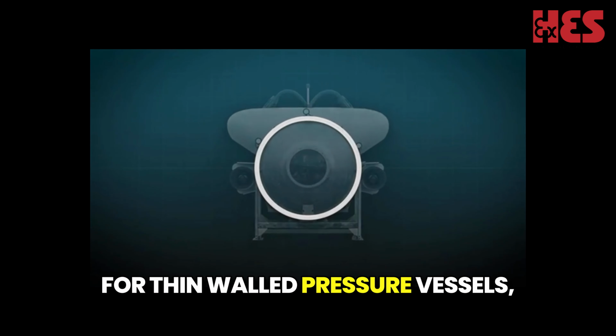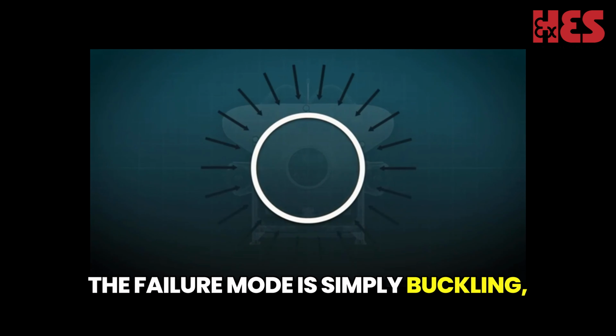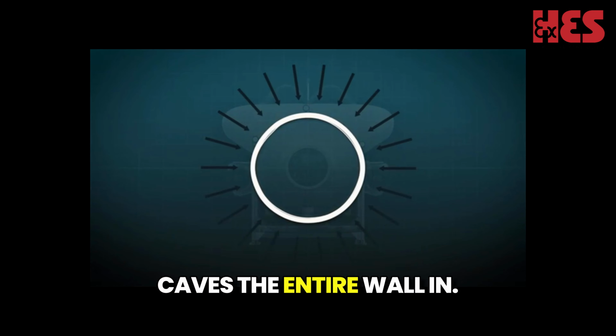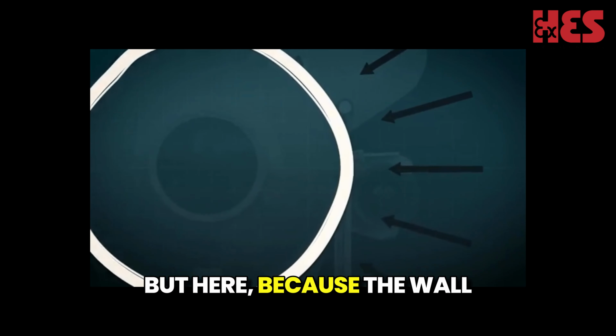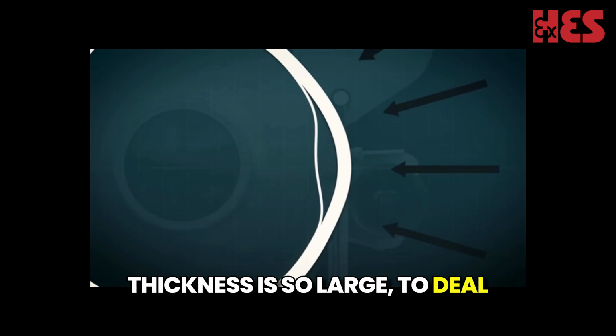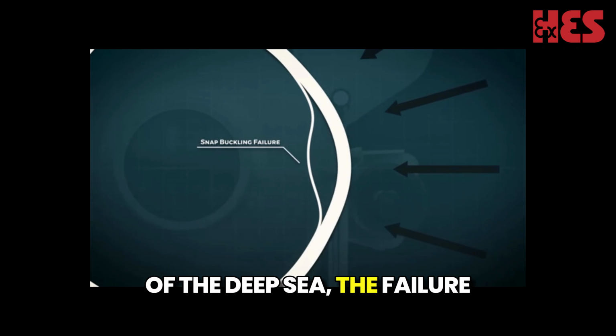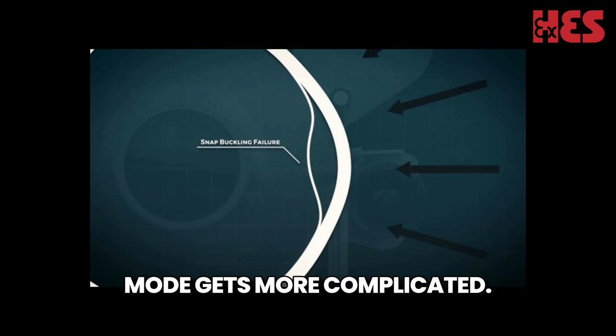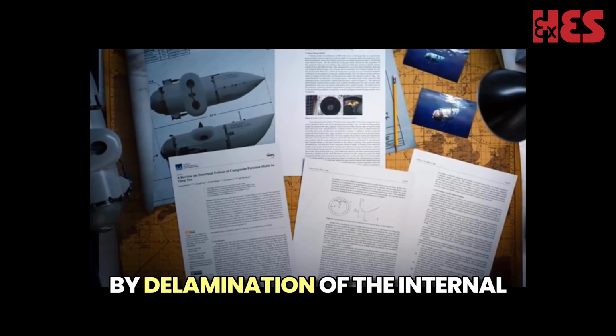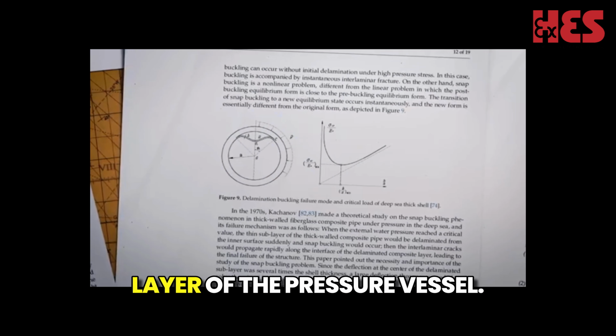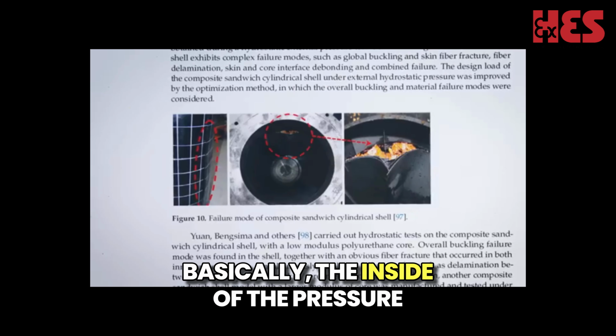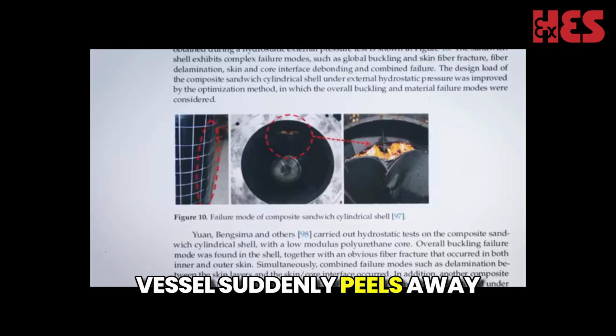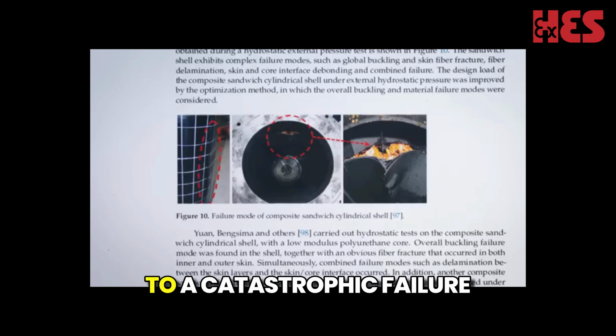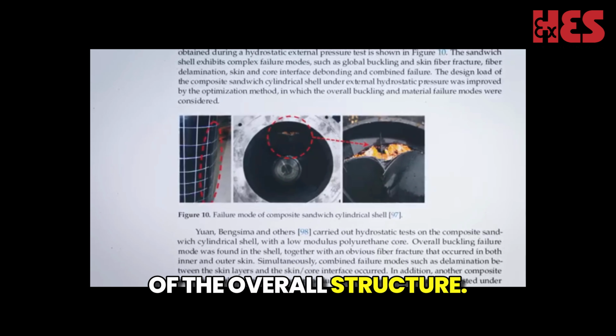For thin-walled pressure vessels, the failure mode is simply buckling, where the pressure simply caves the entire wall in. But here, because the wall thickness is so large to deal with the immense pressure of the deep sea, the failure mode gets more complicated. This failure mode is characterized by delamination of the internal layer of the pressure vessel. Basically, the inside of the pressure vessel suddenly peels away from the rest of the wall, leading to a catastrophic failure of the overall structure.